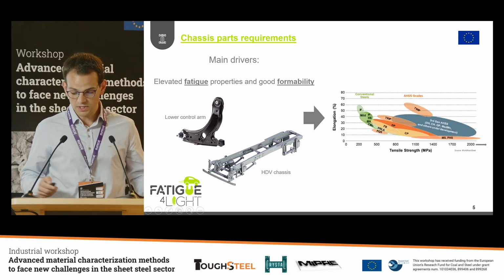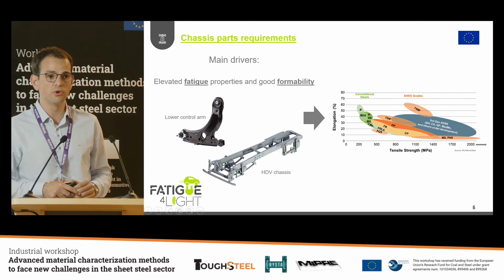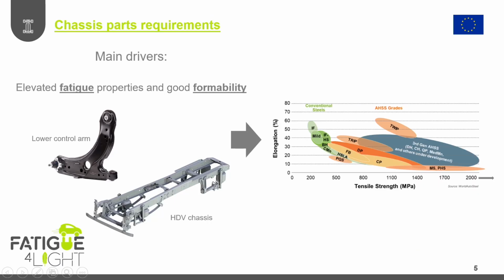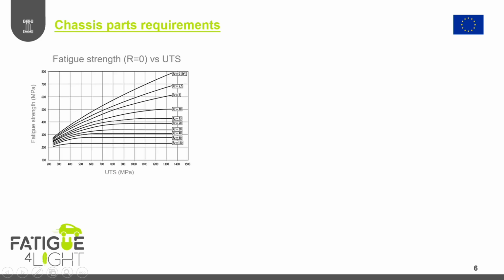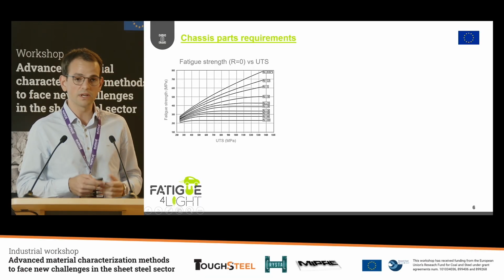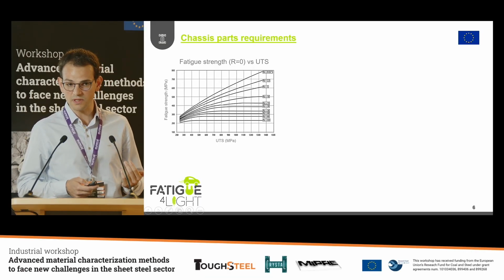So here, the banana plot, if we want to improve this behavior, we can move to a material with a higher tensile strength and with better elongation as well to achieve this lightweight design. But if we move to a material with a higher tensile strength, in theory, we have a good material without defects, so a perfect material, let's say, we will increase also the fatigue resistance of the material, so we can reduce the thickness of the material that we are using.